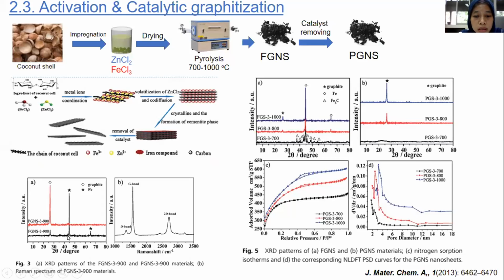This figure is the XRD pattern of the carbonized sample before acid treatment, and the PGNS is after acid treatment. Before acid treatment, the diffraction peak at 26.5 degrees can be assigned as the 002 reflection of graphite, and two sharp peaks at 44 and 65 degrees are indexed to the iron component. After washing with acid solution, the iron component can be removed. The XRD pattern of the sample after acid treatment shows a sharp and narrow 002 diffraction peak, implying the high crystallinity of the sample after acid treatment.